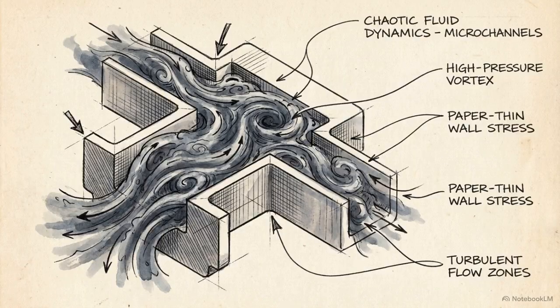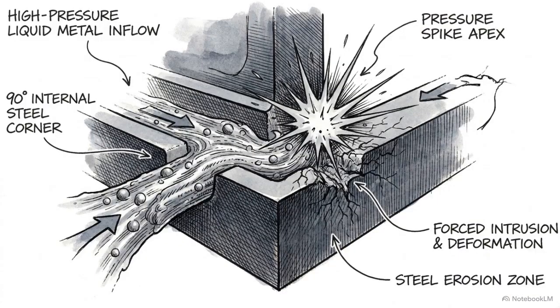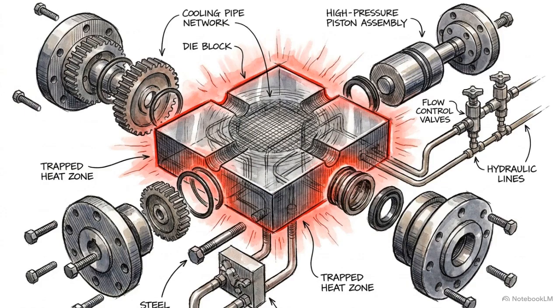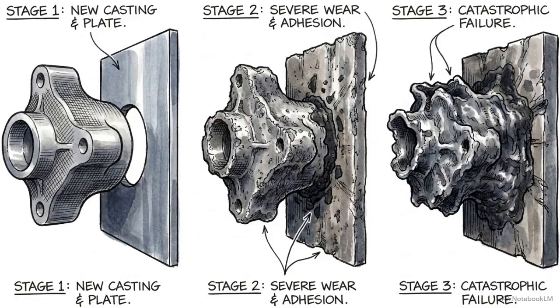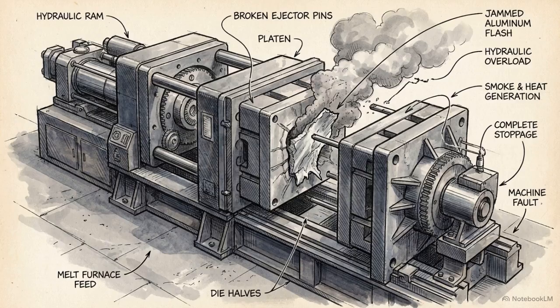Sharp corners and incredibly thin sections disrupt the smooth flow of the metal. This disruption creates localized pressure spikes that force the liquid harder against the wall, further enhancing adhesion. If the internal cooling channels are poorly designed, they will fail to dissipate these localized heat spikes, allowing the intermetallic reaction to sustain itself cycle after cycle. A soldering event indicates a complete systemic collapse across thermal, chemical, and mechanical equilibrium.